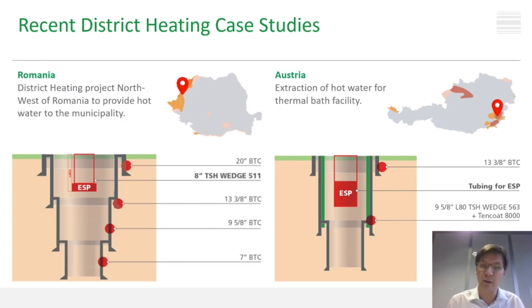For this new well, Tenaris provided a customized solution for the tubing which is holding the electric submersible pump. This solution is an 8-inch Wedge 511, a fully flush solution, and allows to optimize the size of the ESP pump and allows the space in the annulus required to have the cable reaching the ESP pump, bringing the power. Another example is related to Austria, where for a hot water thermal bath facility, we've been working with a customer whose main concern was related to the life of the well, wanting to extend as much as possible the life of the well in presence of CO2 and of sour corrosion.